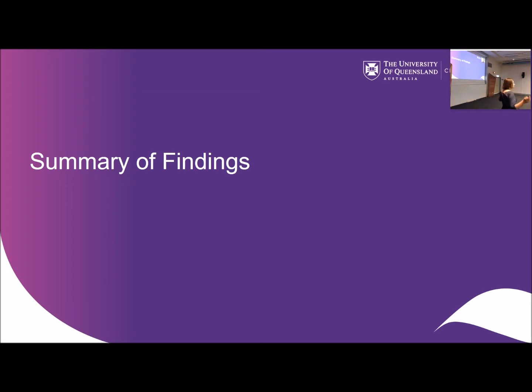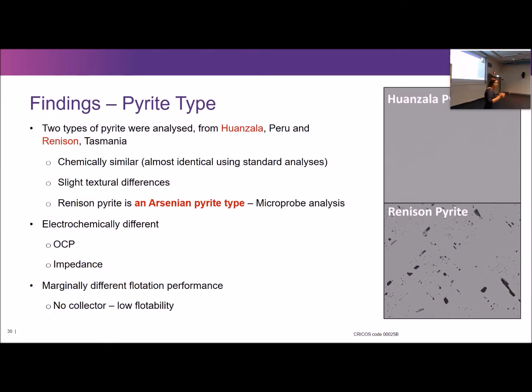So, what does all of this mean? It means that we've analyzed two types of pyrite from Tasmania and from Peru. Chemically identical, visually almost identical with very subtle textural changes. But one is arsenian and the other is not. And they have distinctly different electrochemical activity. We saw this in rest potential measurements, in impedance measurements, and in flotation measurements, but to a lesser degree. One of the reasons for that was, well, we didn't use a collector. We might have been able to see a greater level of difference in the presence of collector and with a greater ratio between chalcopyrite and pyrite in the system.